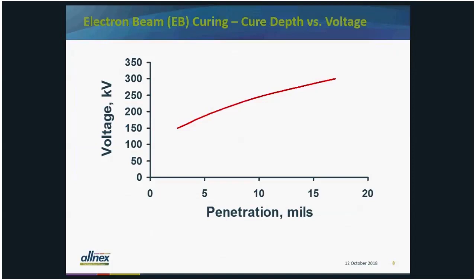And this chart just shows an idea of how thick a coating you can penetrate depending on the voltage of the electron beam machine. So curing 15, 20 mils is not really an issue using EB. Not that you're going to have a 15 mil coating, but you may have some kind of lamination that's going to have a total thickness of that 15 or 20 mils. And that can be done using electron beam, whereas UV is going to be much more of a challenge.